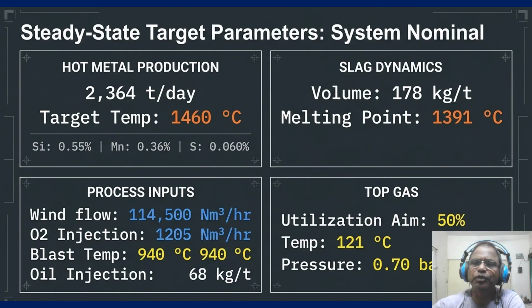So moving forward, these are our flight coordinates for a healthy campaign. On the top left, we aim for 2364 ton of hot metal per day at a target temperature of 1460 degrees centigrade. Now look closely at the slag dynamics box. Our target melting point is around 1400. The factor here is your survival window, the 69-degree delta between iron temperature and the slag freezing point.